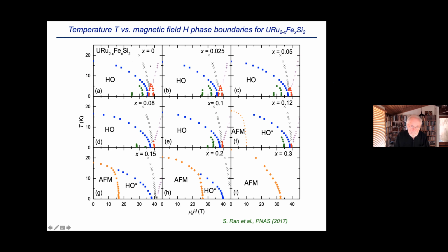And then you get non-Fermi liquid behavior in this region. And over here, you get a Fermi liquid. So then you can anyway see how these evolve. And so you see that there are features, the hidden order transition temperature is changing, the critical field for the destruction of the hidden order is changing, and these features are moving around a little bit, but they're basically the same until you get to this region where the antiferromagnetism cuts in.